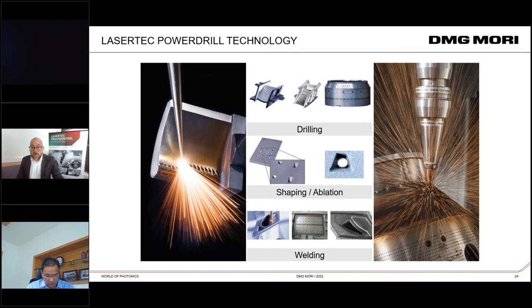If you need to drill, for example, a combustor where usually between 20 to 100,000 drill holes are needed, the old way of producing it was by EDM. By laser machining, we can reduce the cutting time by a factor of 10 to 15. We can drill up to 25 drill holes per second. So this is a synchronous movement of the C-axis of the machine where the part is sitting on, and the laser is giving pulses to that workpiece. So up to 25 drill holes per second are possible.